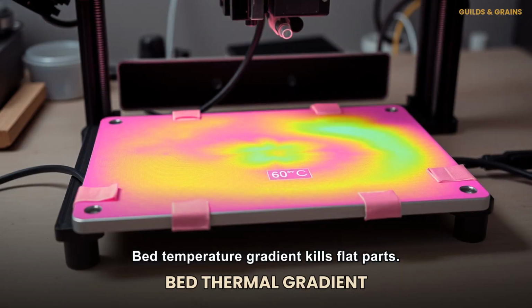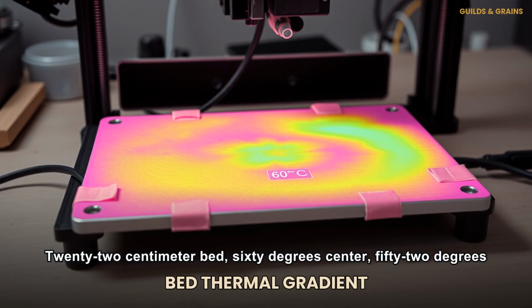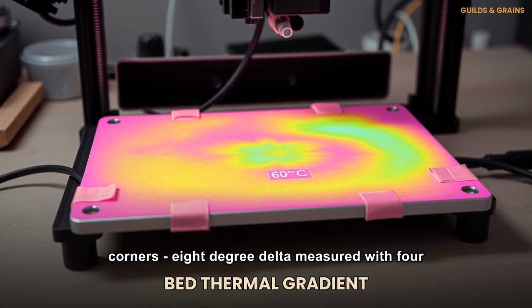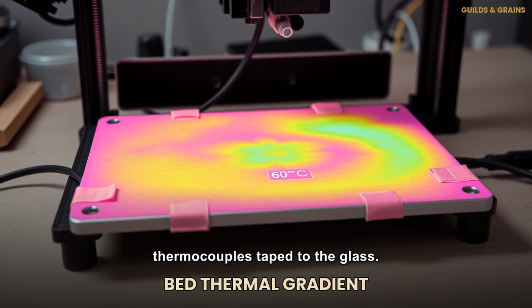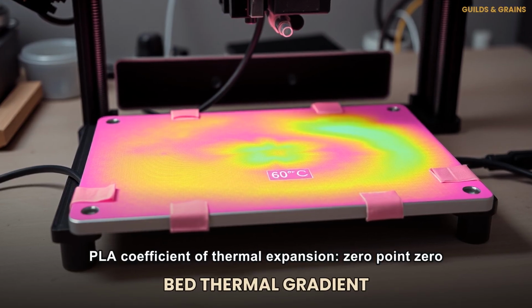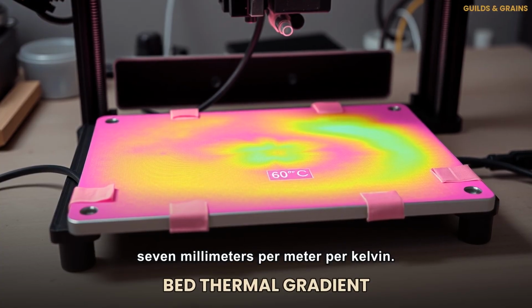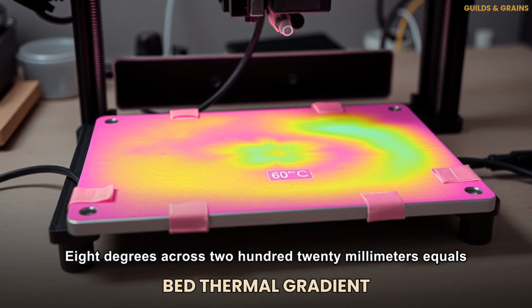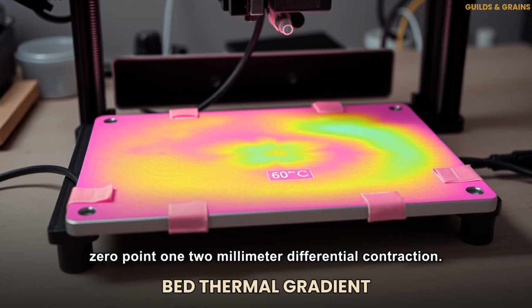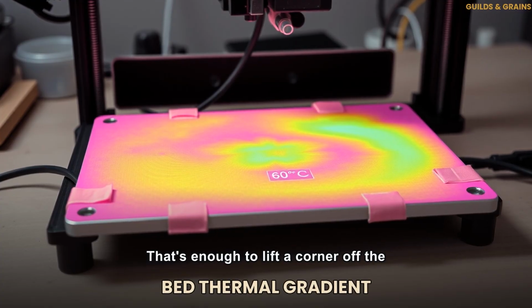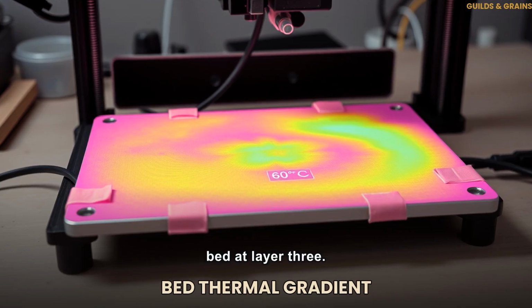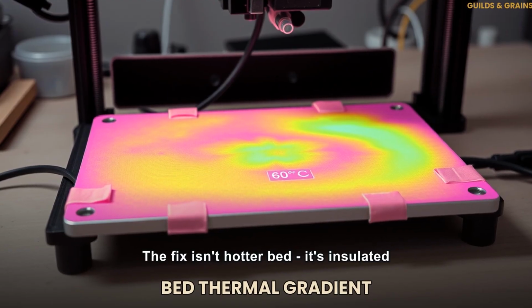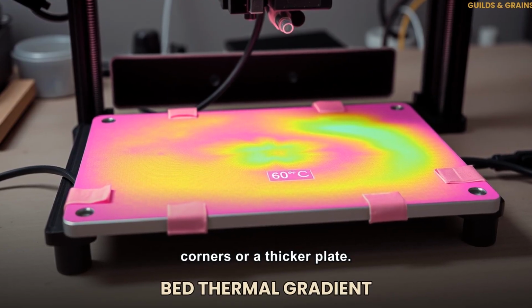Bed temperature gradient kills flat parts. 22 centimeter bed, 60 degrees center, 52 degrees corners, 8 degree delta, measured with 4 thermocouples taped to the glass. PLA coefficient of thermal expansion, 0.07 millimeters per meter per Kelvin. 8 degrees across 220 millimeters equals 0.12 millimeter differential contraction. That's enough to lift a corner off the bed at layer 3. The fix isn't a hotter bed, it's insulated corners or a thicker plate.